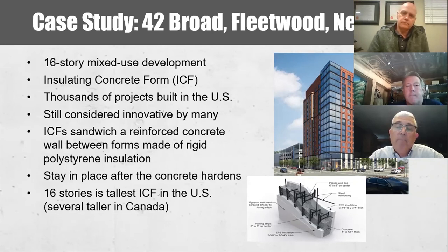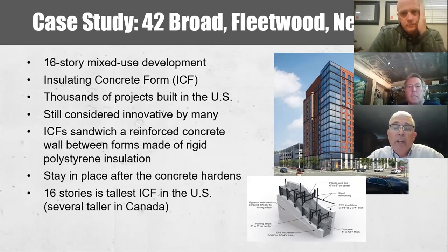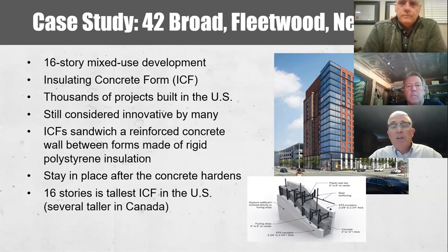And then those web ties, as they're called, also extend almost all the way out to the face of the forming to create flat surfaces that run continually vertically to form furring strips or provide attachment points at regularly spaced intervals, so you can now attach your interior and exterior finishes directly to the formwork. So unlike conventional formwork that gets placed, the reinforcement in concrete is poured and then you strip the formwork away, in this case you're leaving the formwork in place to take advantage of the insulation in the formwork itself, as well as the ability to attach your finishes directly to the formwork and reduce steps in construction.